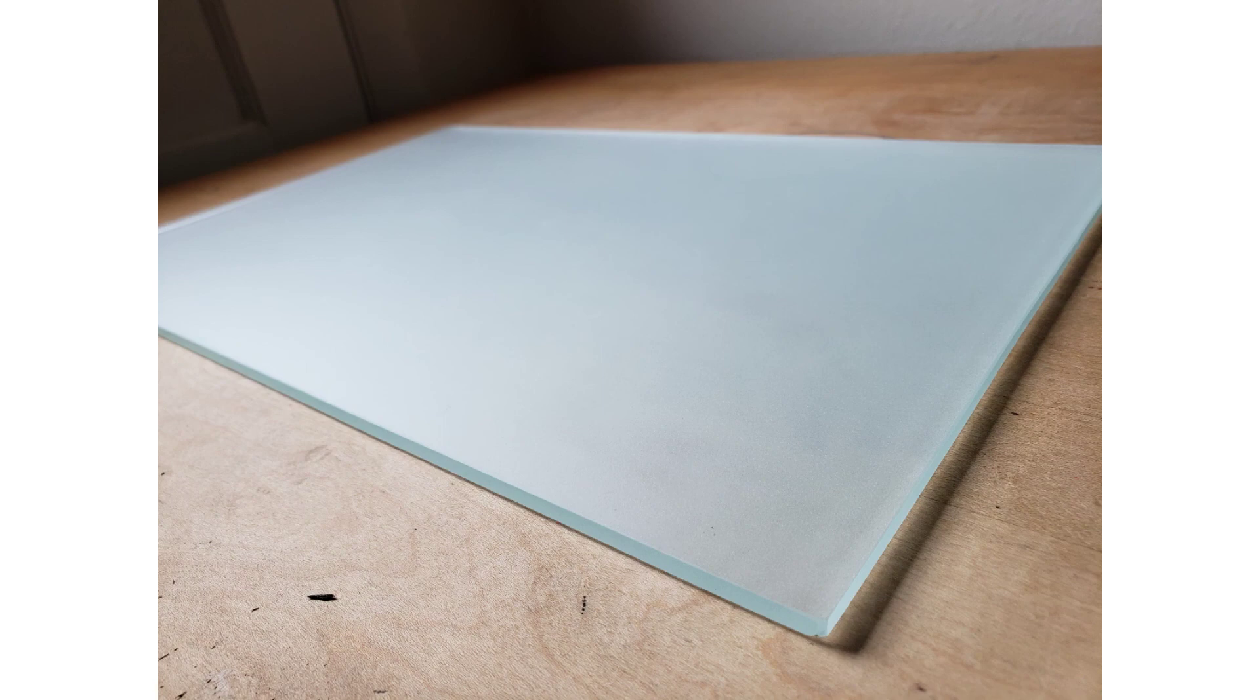This is what a plate looks like when it needs to be grained some more. Notice how the edge is less opaque. This white line is caused by residual carborundum. It could block light and appear on the exposed plate as a gray mark. To remove it, just wash with water. When finished, you will have a beautiful surface ready for drawing.